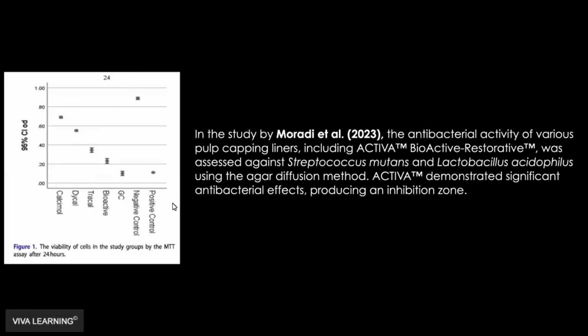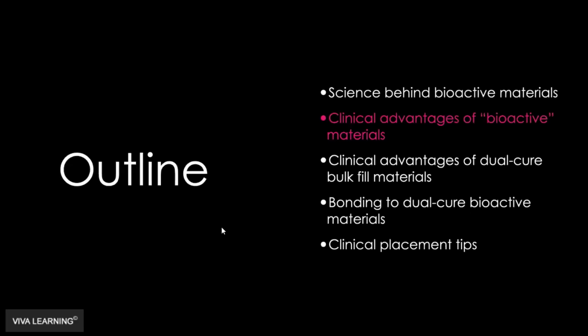And then this is a different study where they also looked at the antibacterial activity of Activa with strep mutans, and what they showed was that Activa demonstrated a significant antibacterial zone. Where is Activa on this? It's right here, Bioactive. So not as much as some of the other materials, but definitely more than the control group. So just more information that this material could be antibacterial.